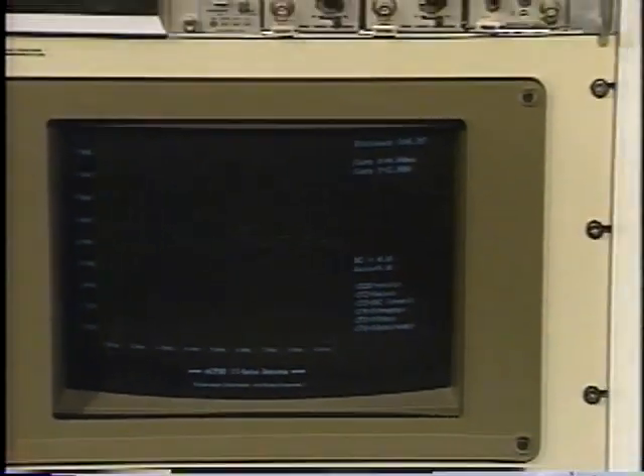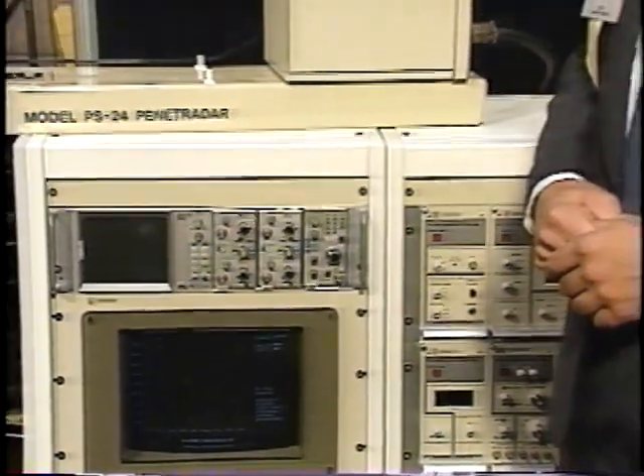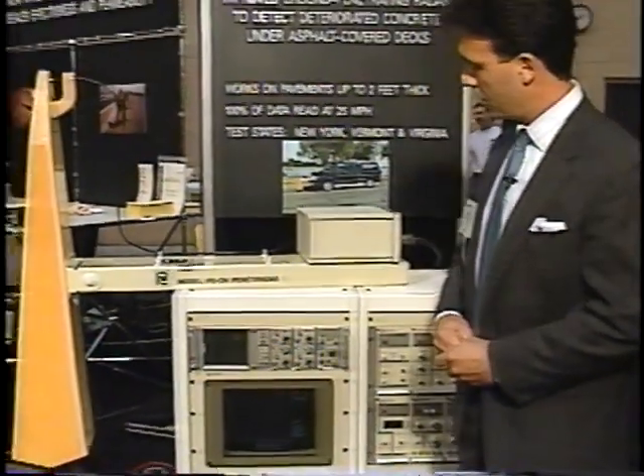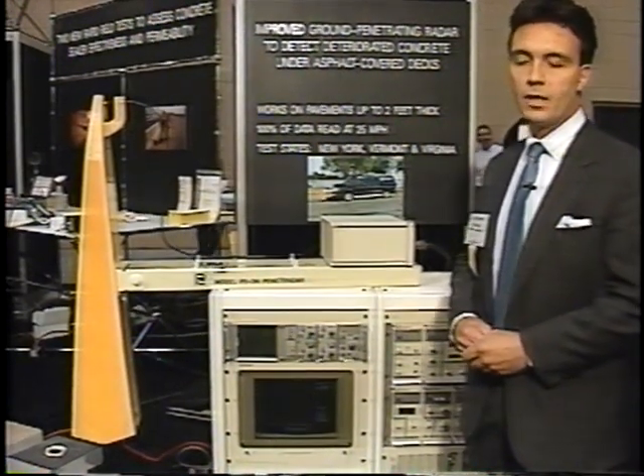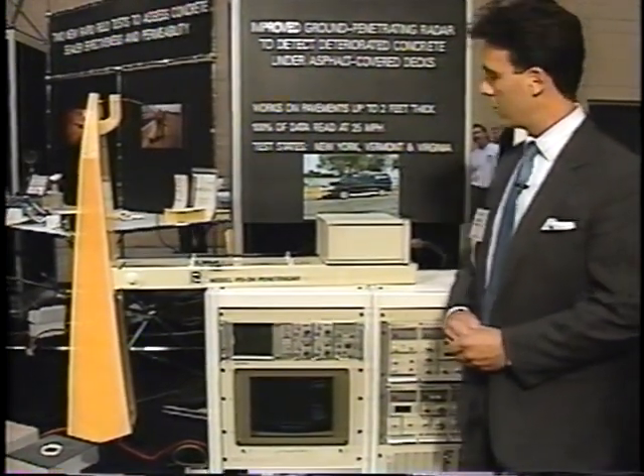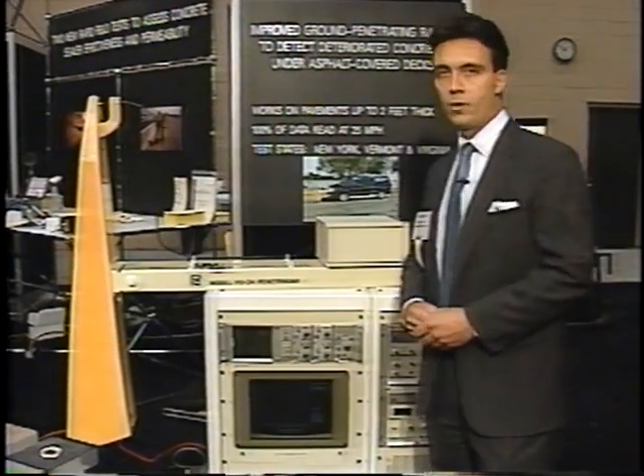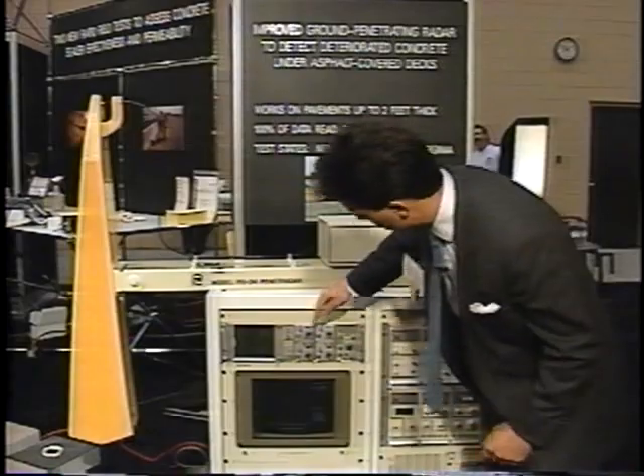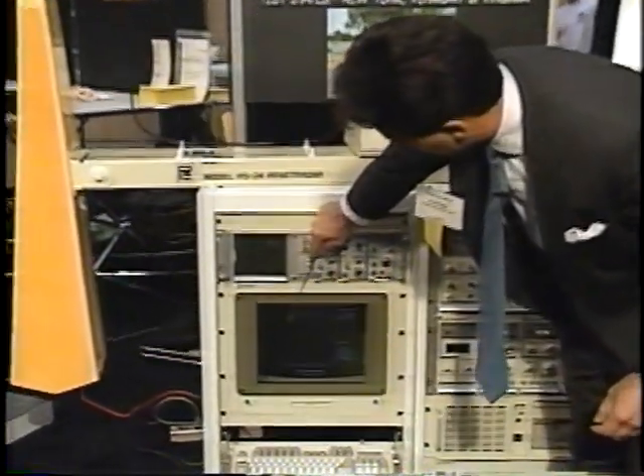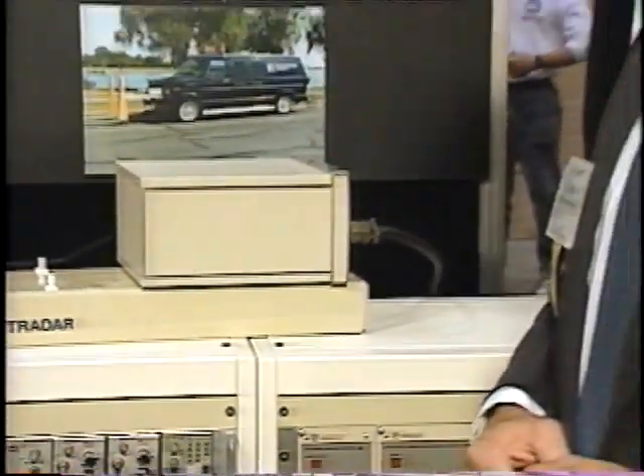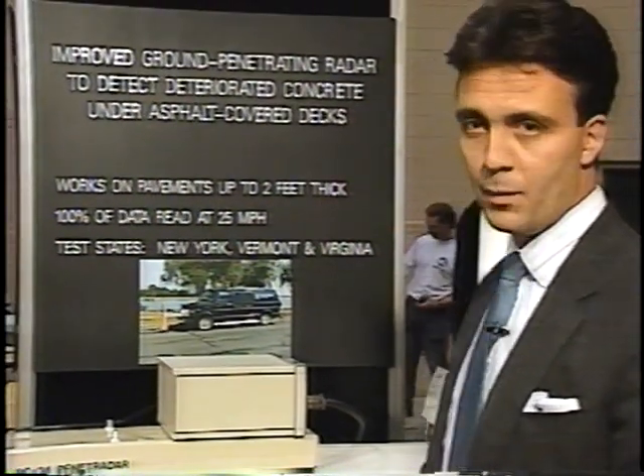For bridge deck delamination, we found that the signal varies in accordance with the chloride and moisture content in the concrete. Accordingly, the signal will attenuate, and the reflectivity at the asphalt-concrete boundary will vary relative to that. So what we look for in bridge deck delamination is an increase in the asphalt-concrete echo, as you're seeing there, and an attenuation caused by the increased conductivity in the concrete subsequent to that. Based on those discriminants or indicators, the computer performs a detection and detects the delamination in that manner.